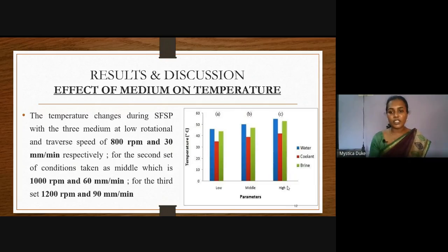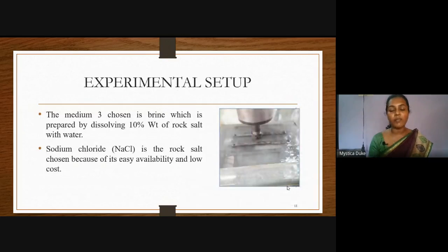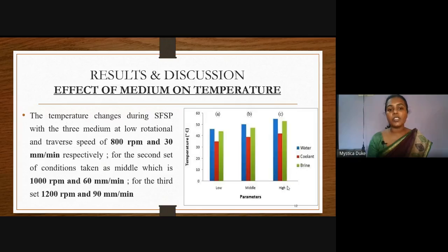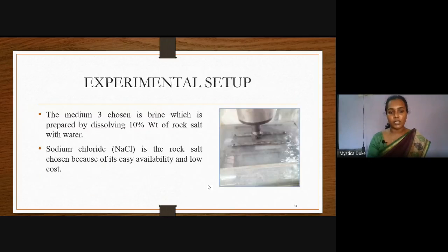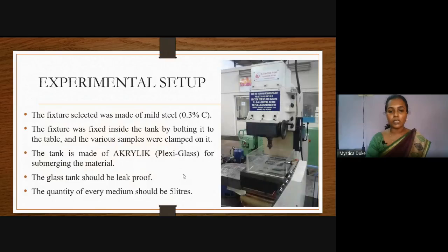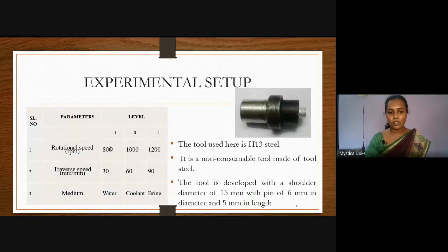So we conducted friction stir processing with all these 3 mediums. We took the samples and conducted a few other tests to analyze how these 3 mediums influence the mechanical properties of the samples. First, we studied the effect of these mediums on the temperature developed during the process. Here you can see the chart. This is the low combination which I mentioned in this table. So this is the first combination, this is the second, and this is the third combination.